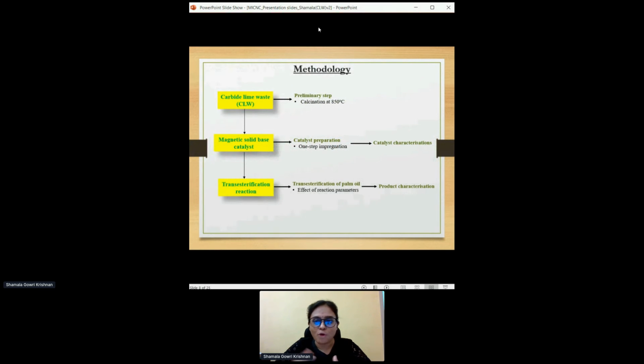Here is the flow of the methodology. We executed a simple methodology where we use carbide lime waste. We calcine it as a pre-treatment process, and then we use the calcined carbide lime waste to prepare the magnetic solid base catalyst by the one-step impregnation method, and we characterize it. Later, we studied the efficiency in the transesterification reaction. In the transesterification reaction, we have a section on the effect of reaction parameters to study the catalytic effect.